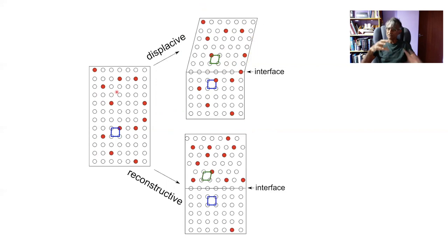On the other hand, you can take the austenite and you can break all the bonds and rearrange the atoms into a different pattern while maintaining the external shape of your crystal. And this has the advantage that you don't cause a lot of strain energy, but it requires atoms to be able to move over a length scale, which is roughly the same as the microstructural scale of the transformation product. And during that process of the breaking of bonds and rearranging them into a different pattern in an uncoordinated manner, the atoms which prefer to be in the product phase will increase their concentration relative to what was there in the original parent region that transformed. Okay, so we may get the long-range diffusion of solute atoms.